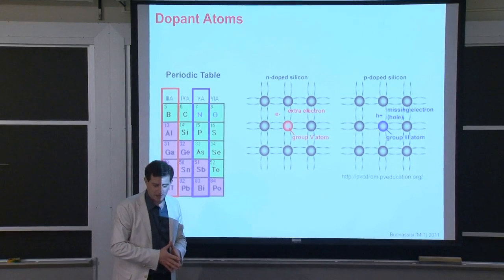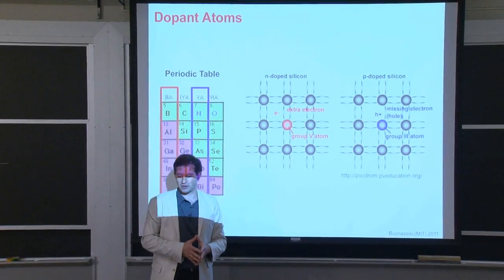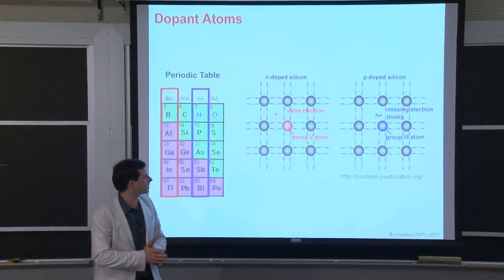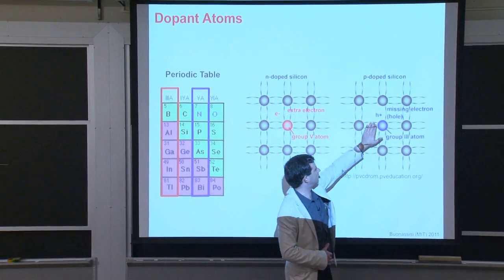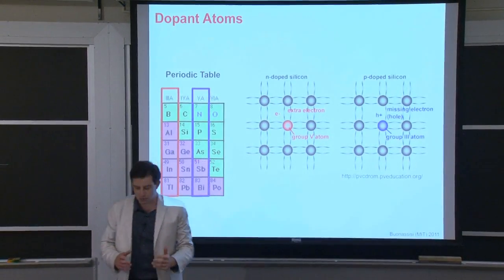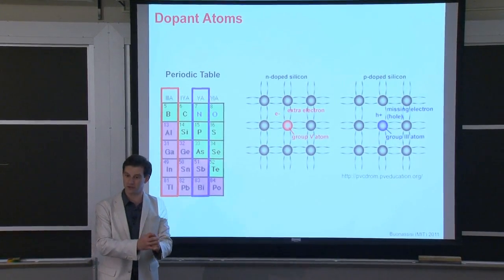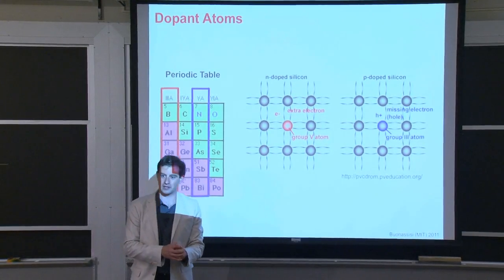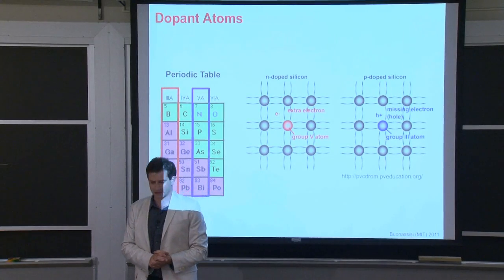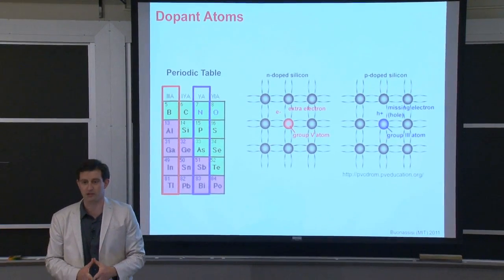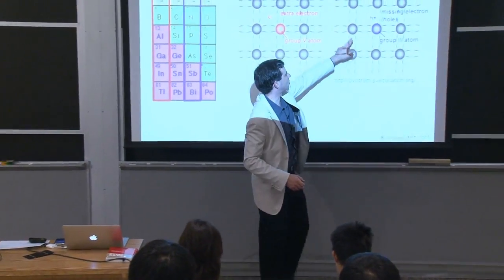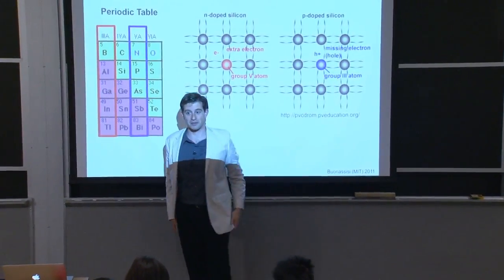Another way that we have very strong evidence that boron is occupying a substitutional site and not an interstitial site is that we can calculate the binding energy of the hole to the boron atom on the substitutional site. In principle, if the interstitial was a charged defect, we could calculate the binding energy of the charge to that defect. And density functional theory could tell you which is more likely, given your experimental observation that you get about one hole for every one boron atom inside of your sample.